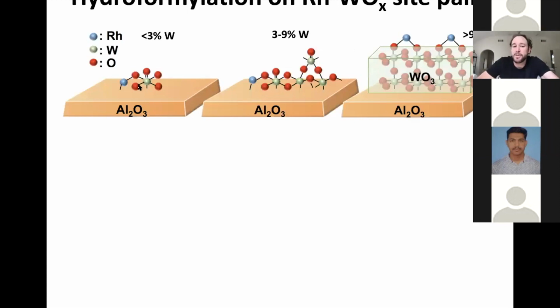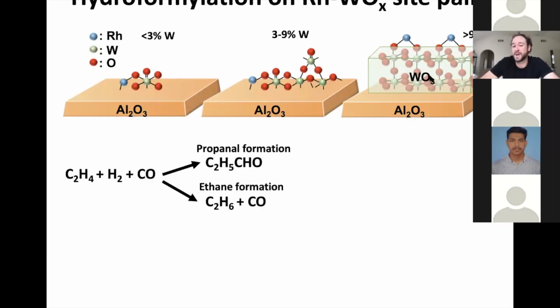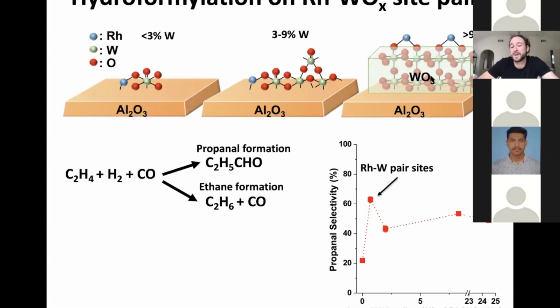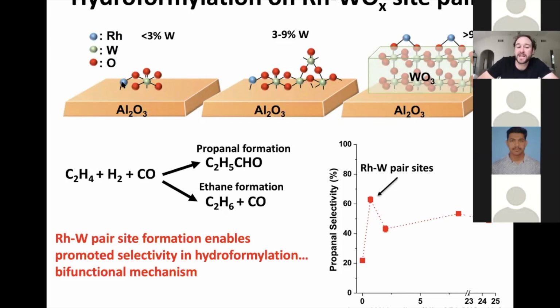And in this last case, I won't go through it in detail, but we've pushed to understand the behavior of rhodium sitting next to one tungsten atom or one tungsten cation, a 2D tungsten domain, and a 3D tungsten domain. We've looked at this in the context of a few different chemistries, but particularly ethylene hydroformylation. And what we see is the pair sites. Only when we form one rhodium next to one tungsten can we see a spike in selectivity. So we can start to say we're beginning to design pairs of sites.